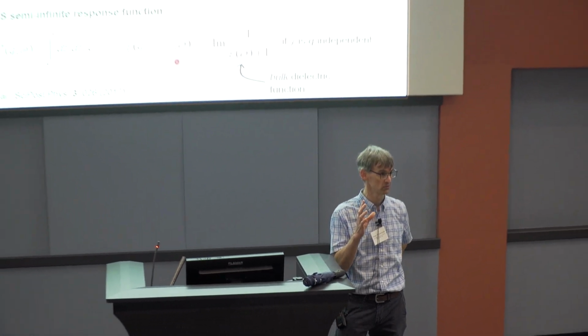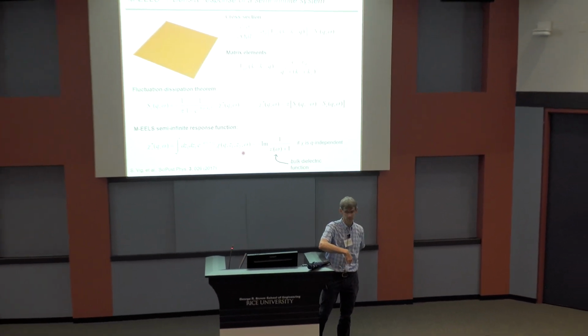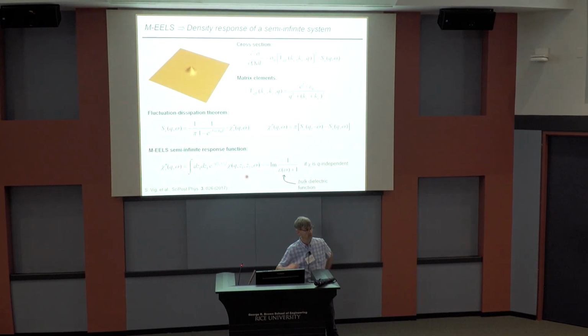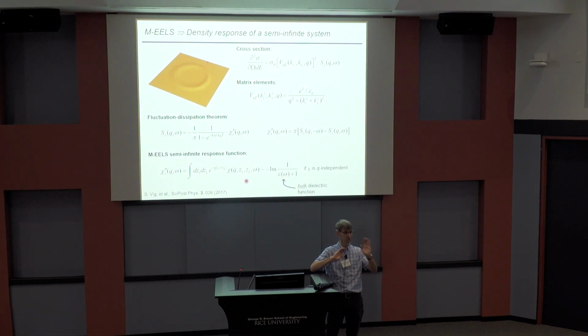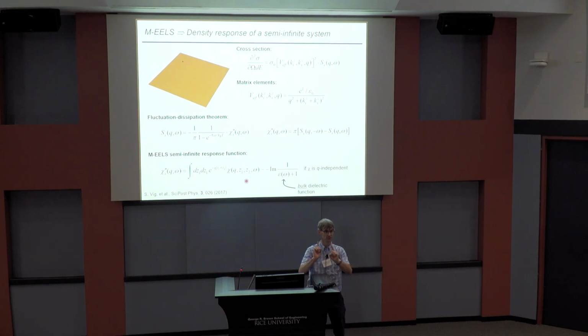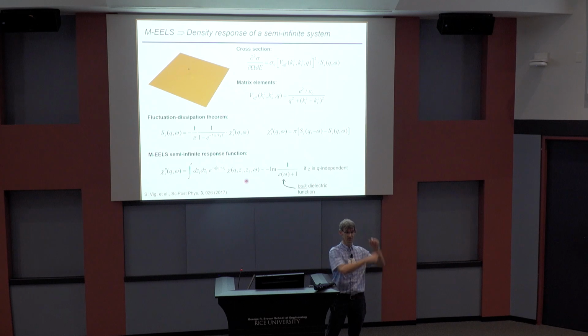This is like ARPES. What we do is we measure a response function. It's an integration of the momentum along the c-axis. We measure this. It's actually very similar to ARPES. Just people have looked at ARPES for so long, they forget that there's a Z, right? But you actually integrate over the Z. So the chi you measure is a mixed one. The Q here is the in-plane Q, and then it's written as a function of the out-of-plane coordinates, then you integrate. So the Jain and Allen approach is exactly what allows you to take a bulk 3D measurement and then compare it to this thing. So that's the best I can do, but they do agree at small q.